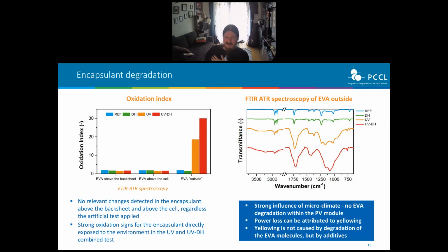The interesting finding was that, apart from the yellowing, the EVA encapsulant in the PV module is not degraded at all. We don't see any change in oxidation index. We don't see any change in infrared spectra or in other measurements. We only saw significant changes in the EVA outside that was not shielded by the glass, because there the UV did its job and really embrittled and oxidized this material. So what we learn is that we have a strong influence of the microclimate in a PV module, and especially the glass has a strong shielding effect, so that the encapsulants usually don't degrade that much.